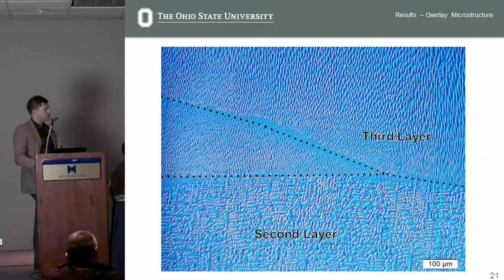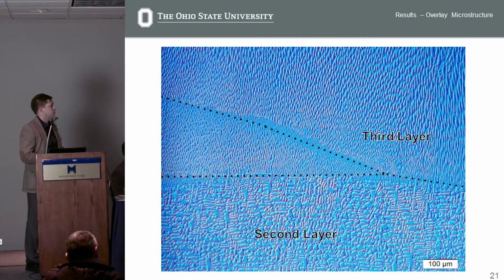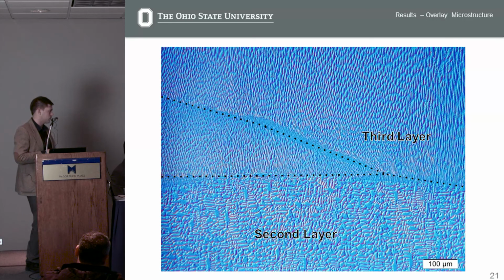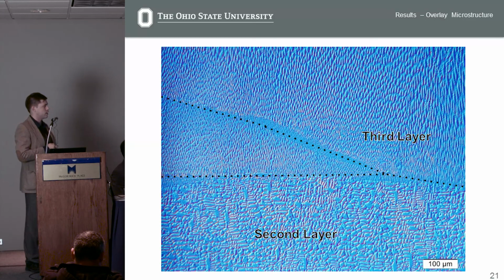The microstructure of the overlays indicates a coarsening of the microstructure as the dendrites solidify upwards from the previous layers. And as each subsequent layer is laid on top of one another, the microstructure resets and just goes from small to large again, and then small to large again.